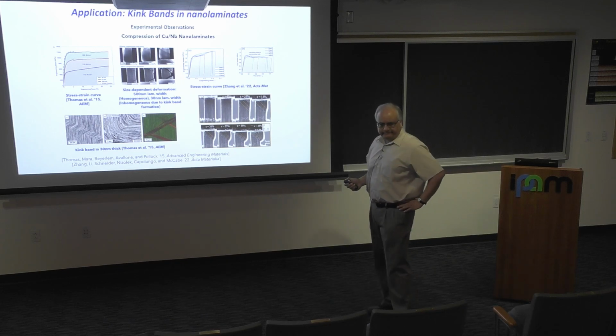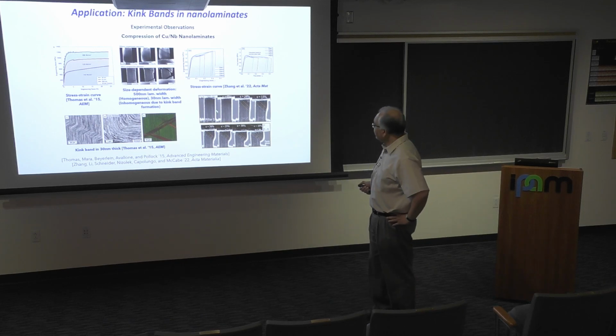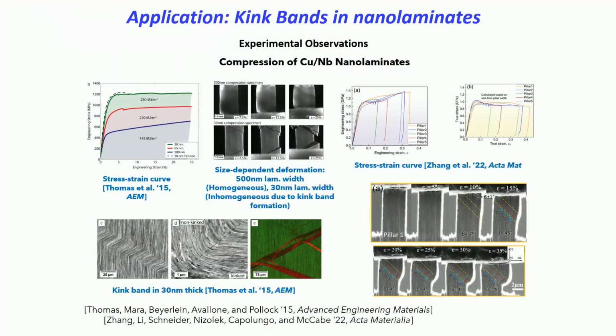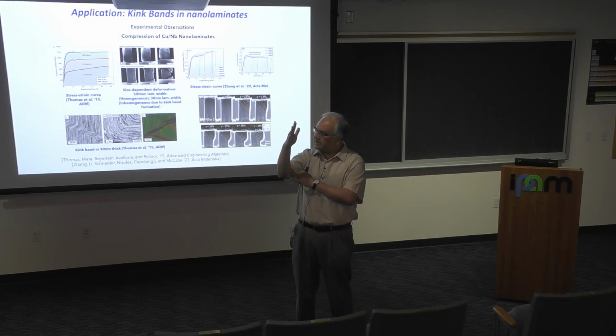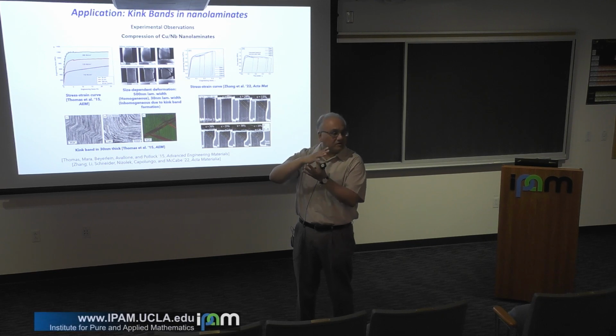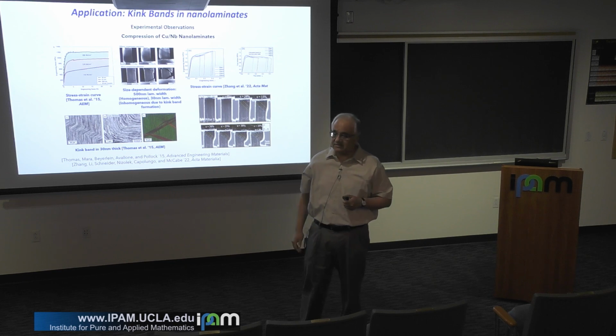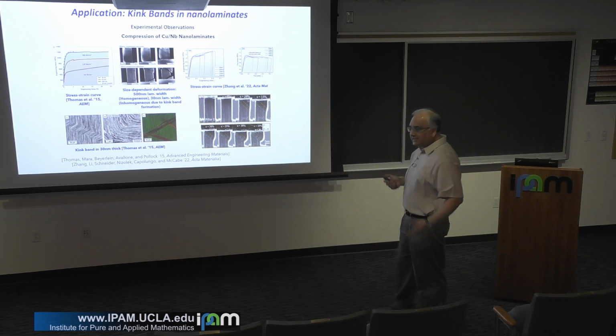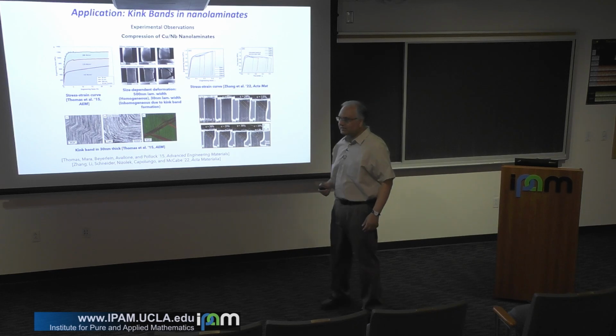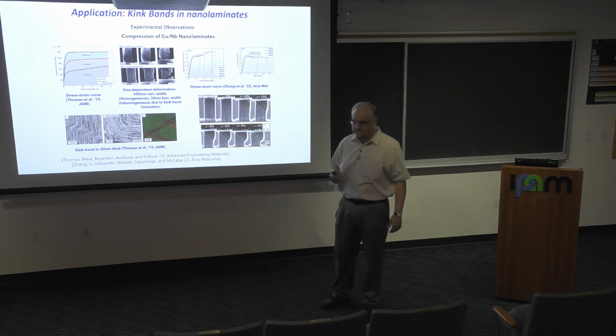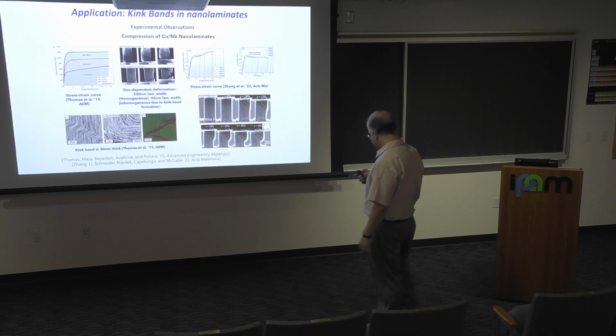Predict that. And these are close-ups, so this is the kink band. You see at 30% strain, so it was being compressed. And so a kink band is essentially, if you have layering, some sort of layering, and deformation localizes transverse to the layering, you call it a kink band. If it localizes along layers, or if there are no layers but along the shear direction, that's called a shear band. Okay? So these are a few things you want to predict, and you can see the size scales. So those are the questions, right?